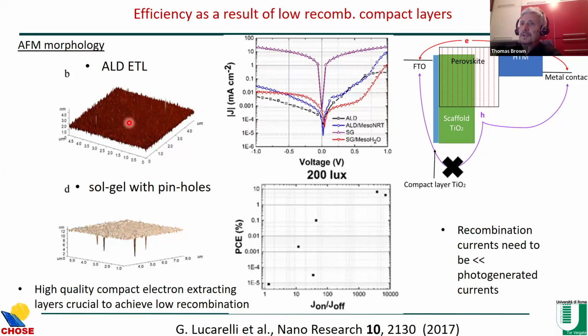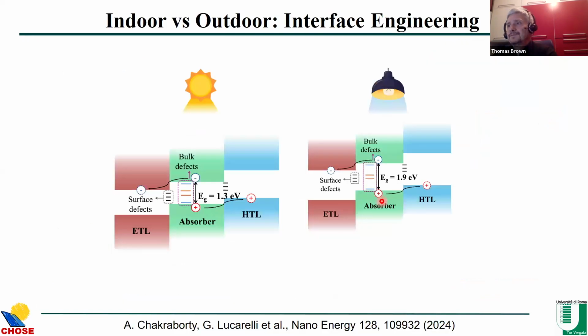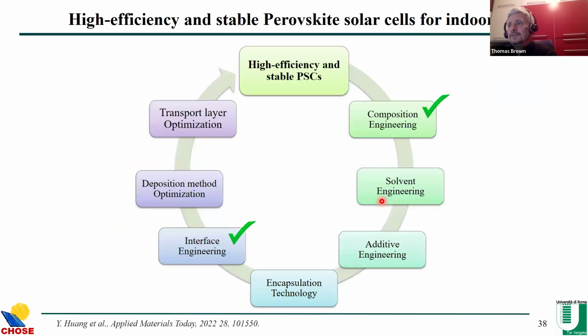Whereas for ALD devices, hardly any pinholes. I mean, they weren't visible in this AFM. The recombination current was 3 to 4 orders of magnitude lower compared to sol gel. That's why they work so well. So they're blocking recombination of holes and electrons at this contact. Recombination currents need to be much less than photo-generated currents. So because the optical powers under 200 lux are very low, you want recombination currents to be at least 10 to 100 times lower. Actually, we find that 100 is a good factor because below that, the efficiency isn't so good. Above that, you can get good efficiencies. So you need recombination currents to be 100 times lower compared to the photo-generated ones to achieve good efficiency.